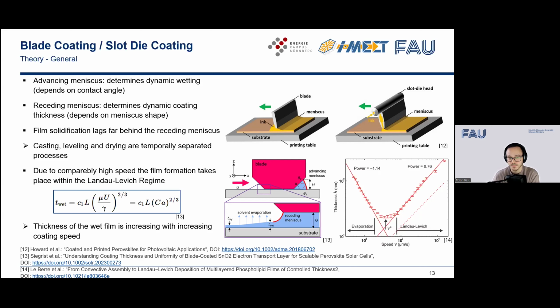So the film solidification lags far behind our receding meniscus because we're not in the evaporation regime. We're in the so-called Landau-Levich regime for our typical coating parameters. And this regime has a distinct feature: by increasing our coating speed, we end up with thicker layers, which in the beginning sounds a little bit counterintuitive, but that's how we can adjust the thickness of our coatings.